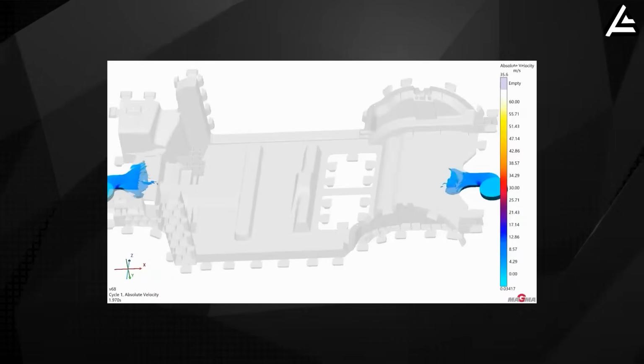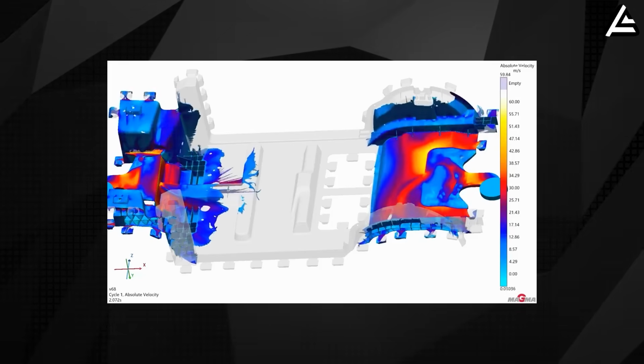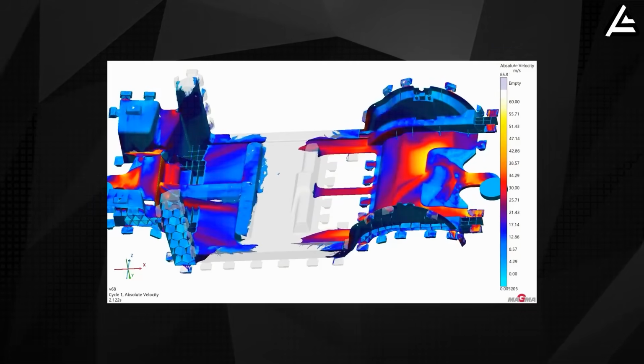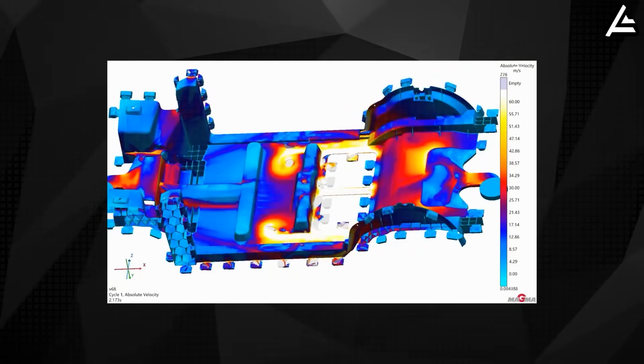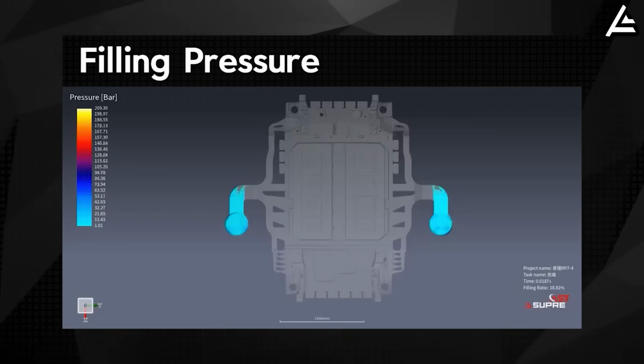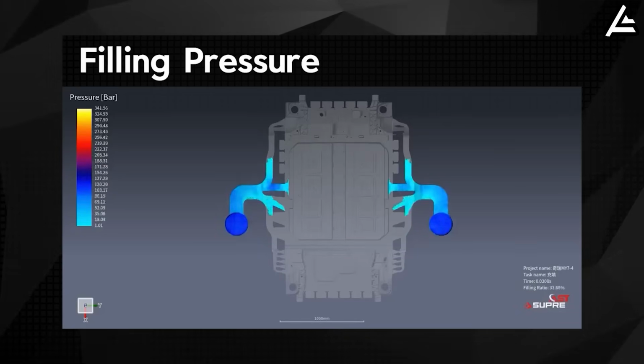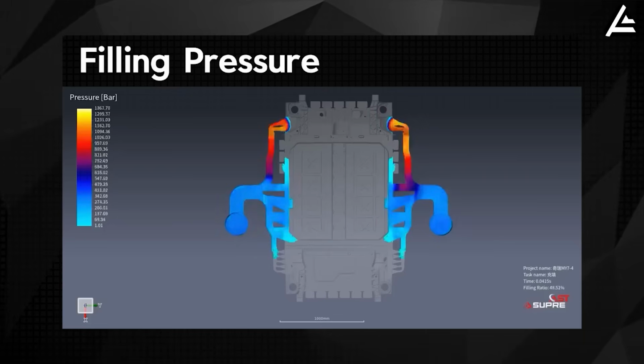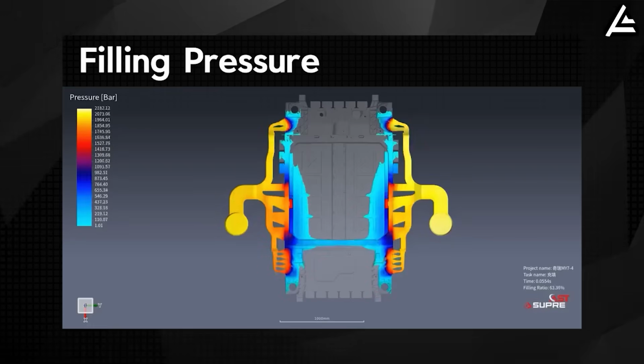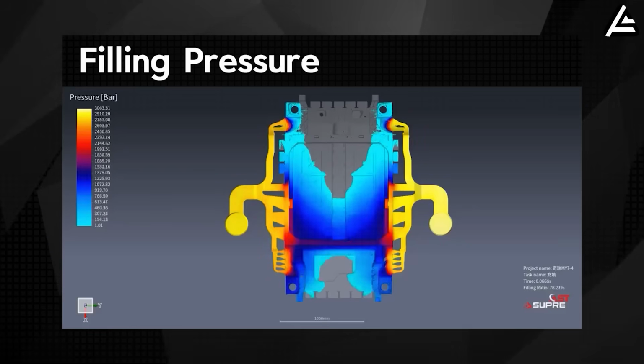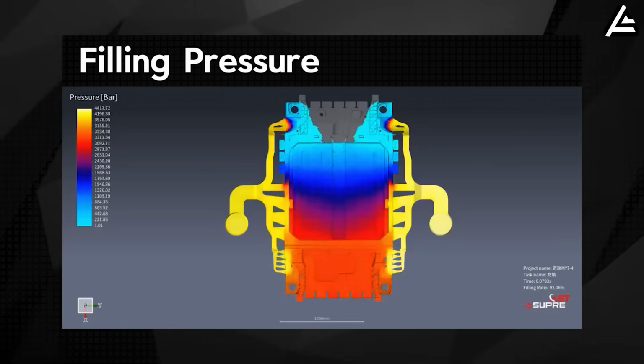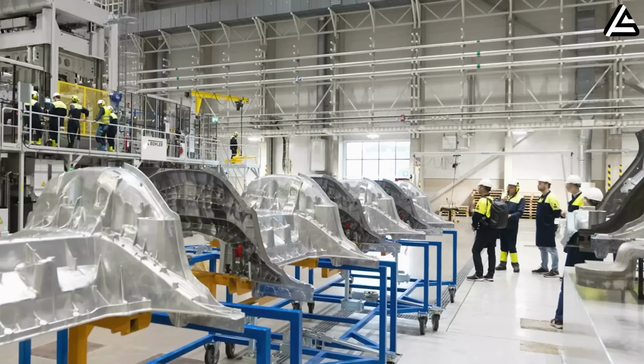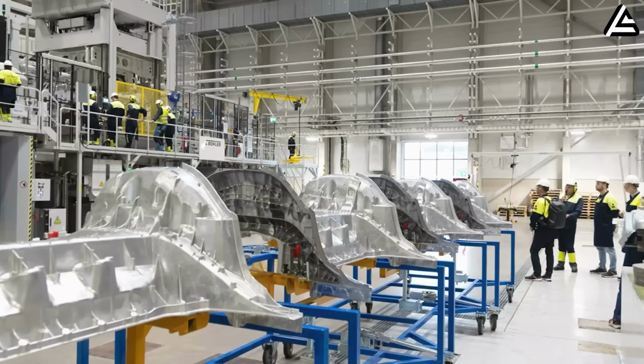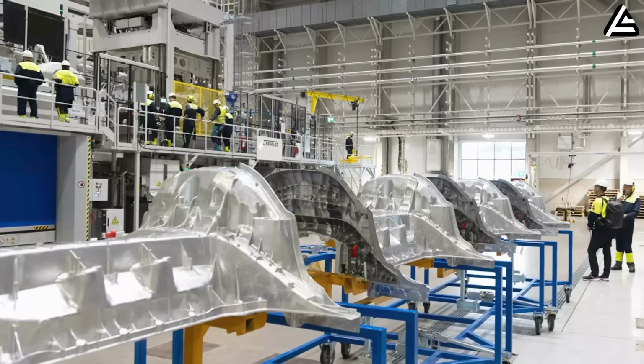The molten aluminum is then injected into the mold at about 10 meters per second by the high-speed piston, generating up to 61,000 kilonewtons of pressure. The force and speed must be precisely controlled to fill every detail without defects while maintaining monolithic structure. Technical analysis shows that with the piston speed, vacuum system, and special release coating, dimensional error can be kept below 0.1 millimeter, ensuring the Model 2 frames remain consistent and meet strict engineering standards.